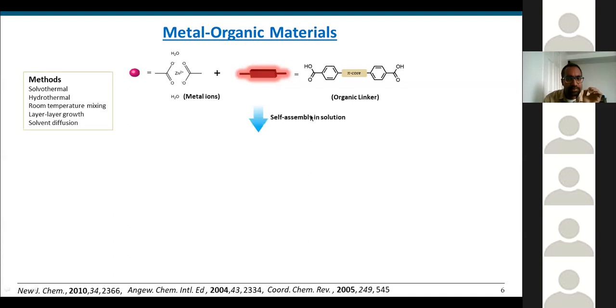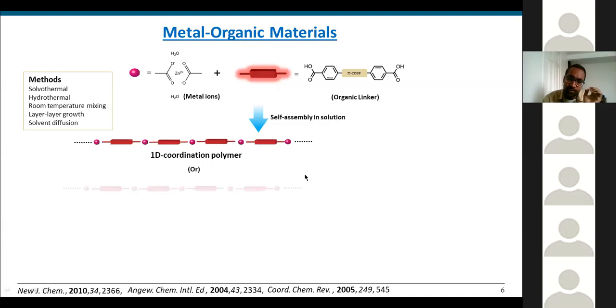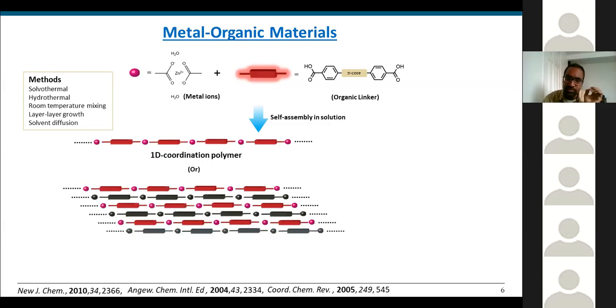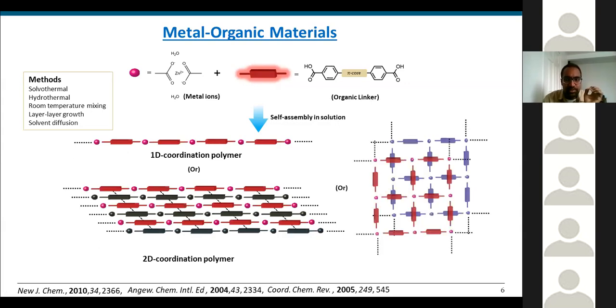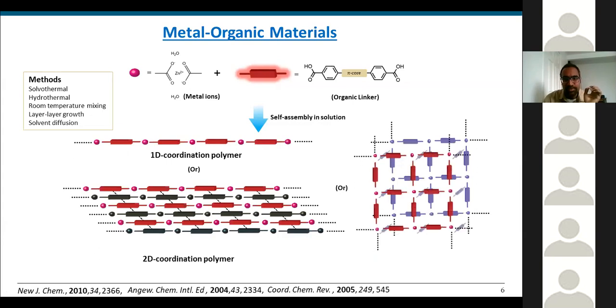Now, when we assemble them in solution, they can form one-dimensional coordination chains, where the primary interactions are coordination interactions. These coordination chains can further interact through supramolecular interactions to form a two-dimensional coordination polymer. Or they can form a network-like structure, which is three-dimensional and porous in nature, called a three-dimensional coordination polymer, or metal organic framework, also called a hybrid inorganic organic material.